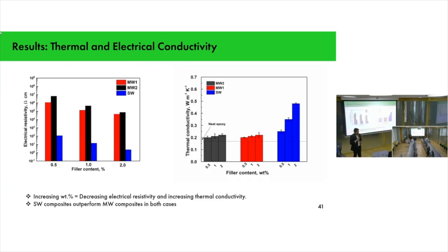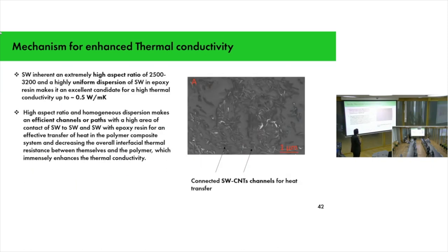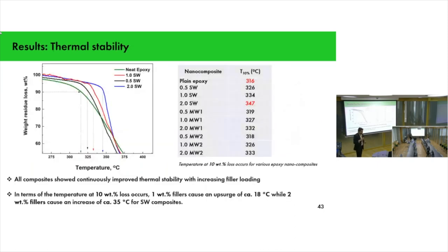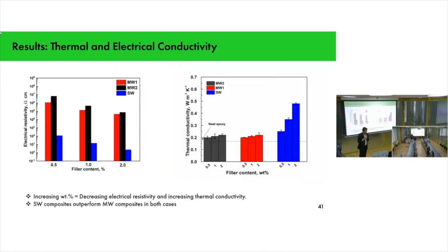Here we see that when going into thermal and electrical conductivity, there is an increase of thermal conductivity as well as a decrease in electrical resistivity when you are increasing the weight percentage of all of them. But the best thermal conductivity was shown by the single wall carbon nanotubes, almost 0.5 watts per meter Kelvin with just 2 weight percent filler content. So we can say that single wall composites outperform the multi wall composites in both cases.